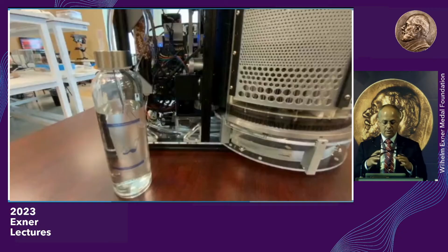So our plan is to not just look at kitchen size, but also a device that sits outside the home to provide enough water, and also what I call village scale devices. The point is that the MOF works, and this device has been working 200 cycles a day for the last 2.5 years, and the MOF still works. So the MOF is rated to stay in the device for about 5 to 6 years. That's 200 grams of MOF.